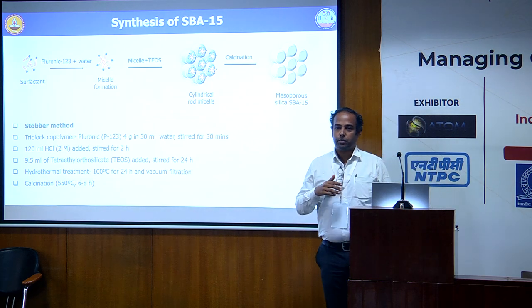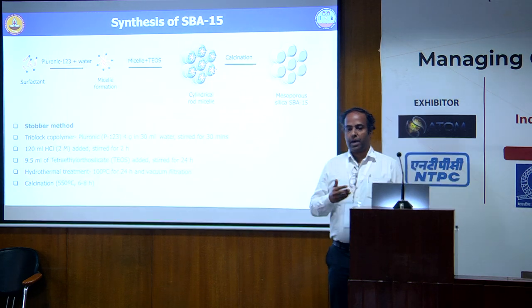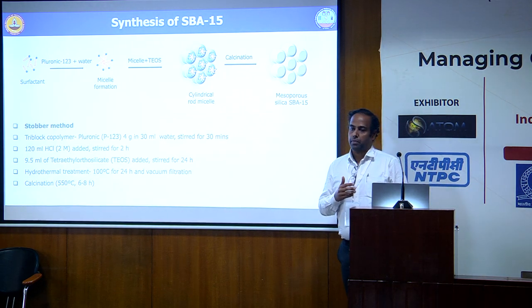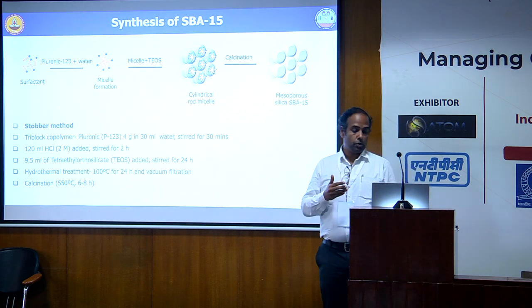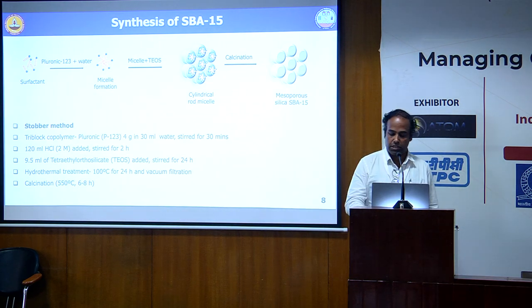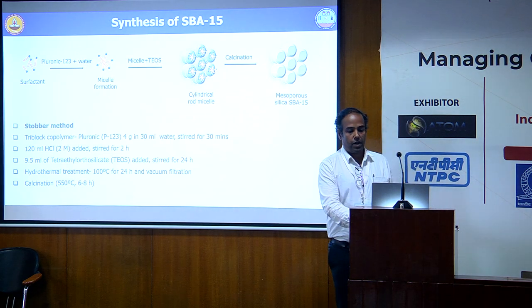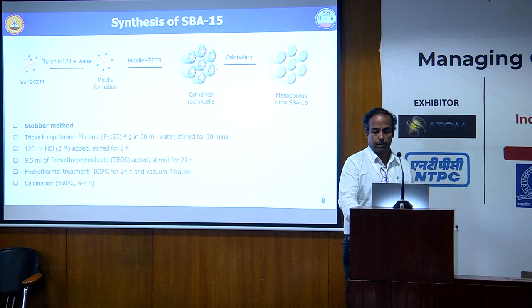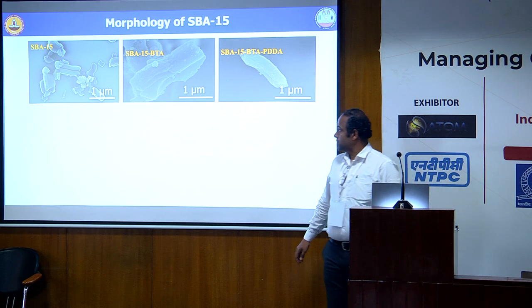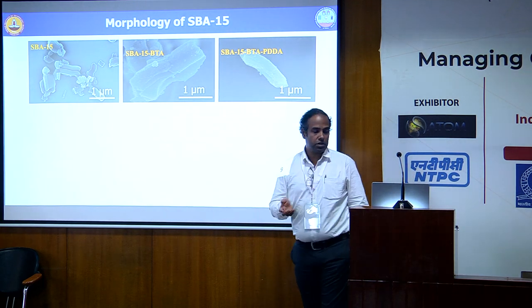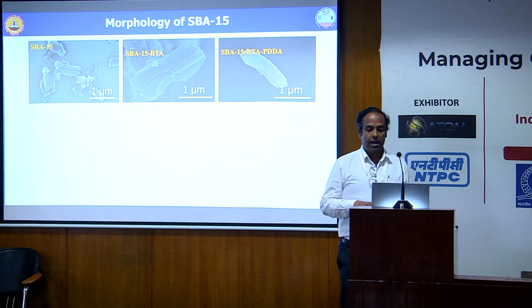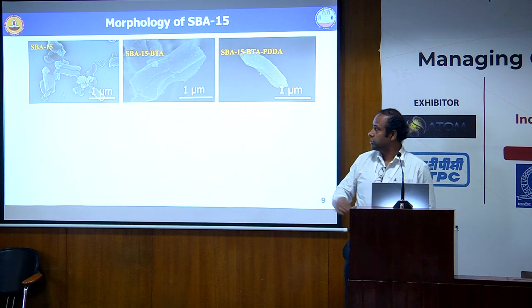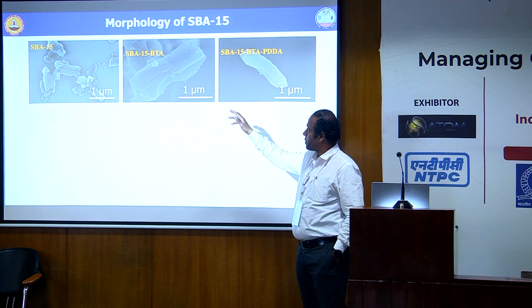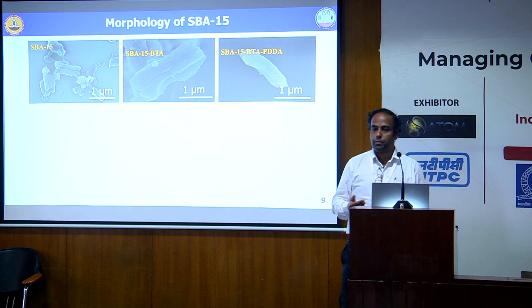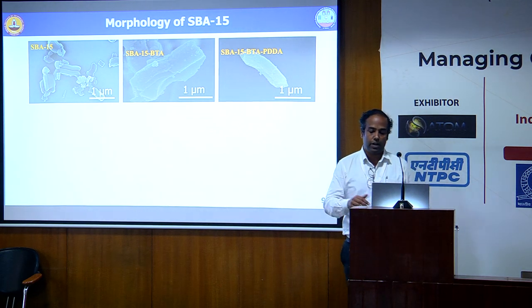How do we go about it? Simple colloidal chemistry, where you prepare SBA. SBA stands for Santa Barbara Amorphous 15, which is a mesoporous silica with certain dimensions, produced by the Stöber method process. So finally, once you get the particle, how does it look? This is how it looks. It's basically cylindrical, approximately 15 micrometers in length. What we have done is, first, the as-received, as-produced particle, and then we try to mix it with BTA, which is benzotriazole, one of the well-known inhibitors.